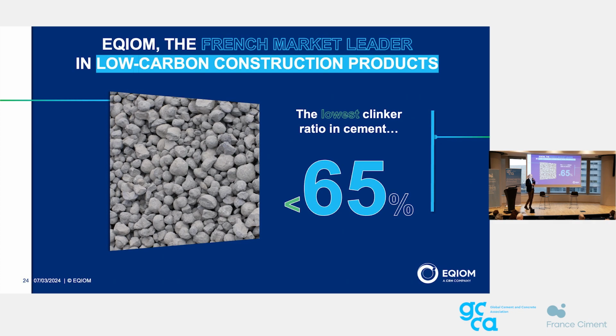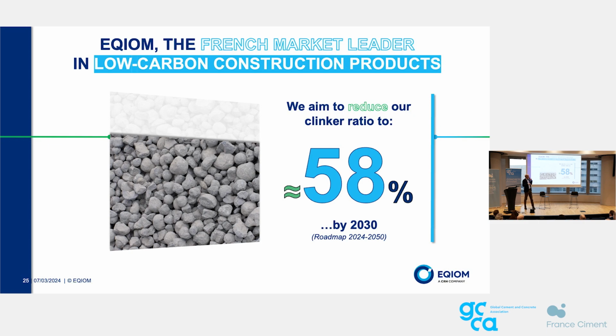How do we get there? As we were mentioning, most of the CO2 emission in the concrete is coming from the clinker, from the cement part. Ekiom has the best clinker ratio on the French market among the traditional cement players. We have a clinker ratio in our cement, on average, below 65%, the best one on the market. We've been using slag for more than 30 years. We are still planning to decrease that clinker ratio and to improve our environmental footprint. Our target by 2030 is to reach 58%. And despite the slag scarcity that may happen in Europe due to some transformation in the slag industry, the use of calcined clay, the use of fly ash, and the better use of limestone, for instance, should help us to reach that level.